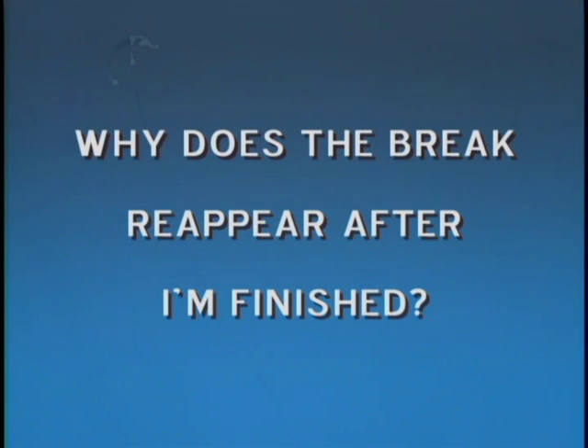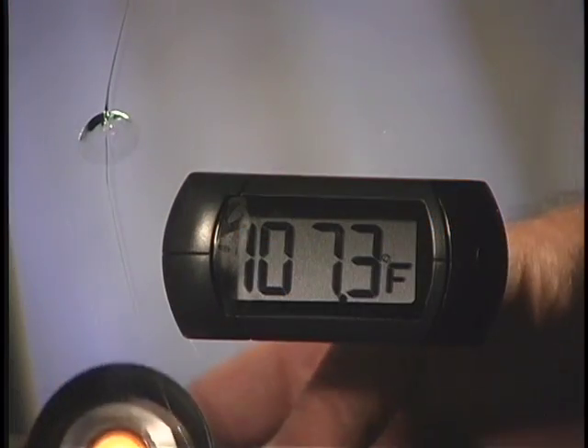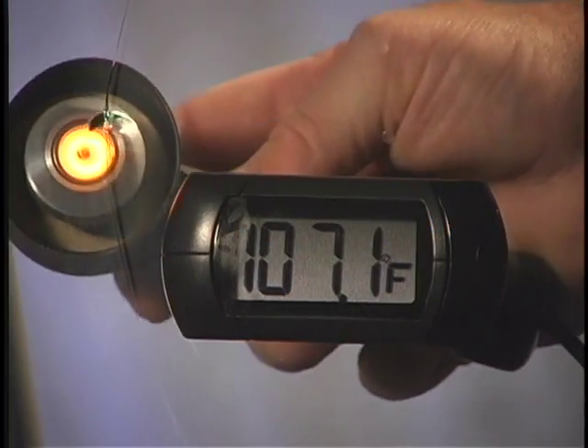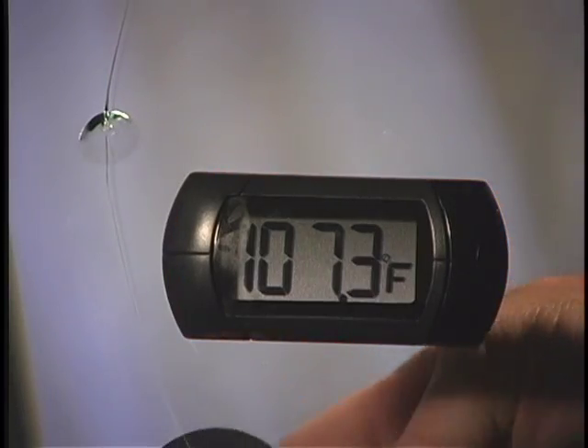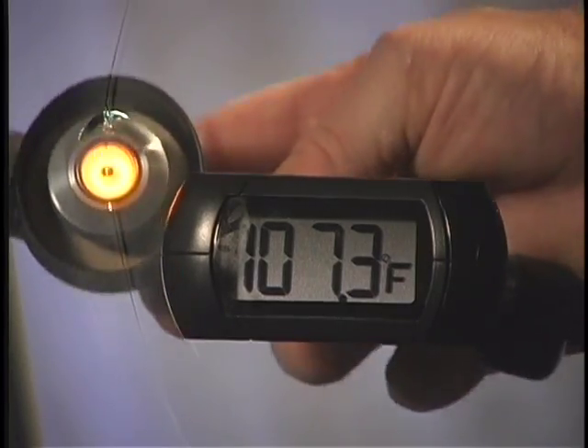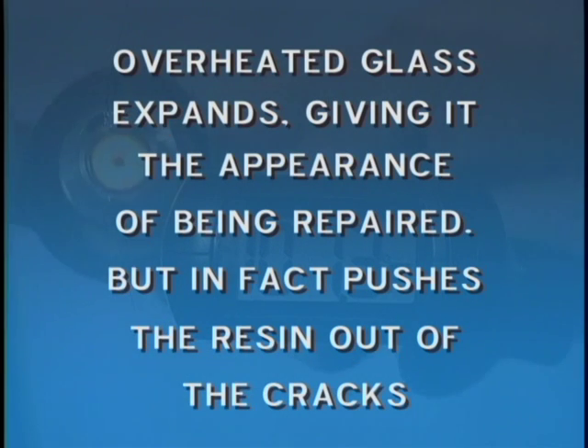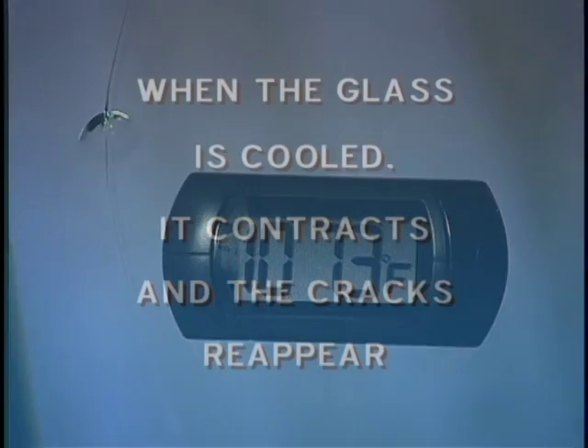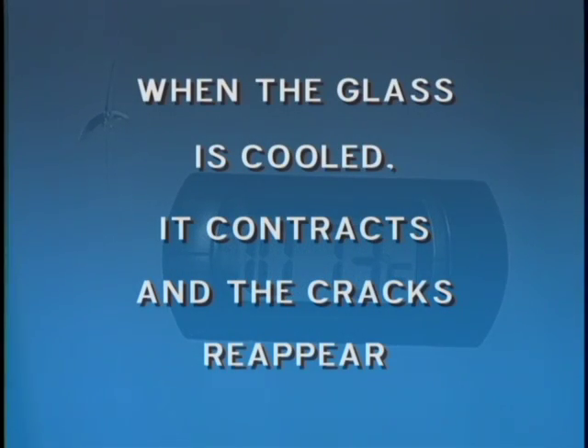When I finish a repair, it looks great, but later it seems to reappear. There are two common causes for this problem. One is overheating. When the glass is warmed past the ideal temperature of 80 to 90 degrees, it expands, pushing the resin out of the crack. It looks repaired, but in fact has no resin in the cracks, thus no bonding strength. When the glass is cooled, it contracts and the cracks reappear.